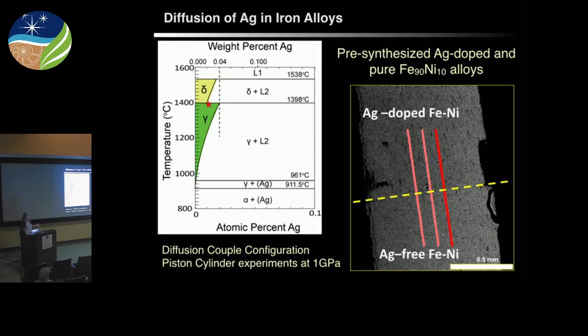Okay, so we did something similar. We did diffusion experiments again. These are a bit more traditional diffusion couple experiments that were measured using the electron microprobe. The one thing that was a bit difficult about these experiments, and I was surprised by this when I first started learning about it, is that silver is super not soluble in iron at all. Here's the iron-rich area of the iron-silver phase diagram, and this is atomic percent silver, and this is the region you have to be in to get silver dissolved in your sample. There's not a lot of silver in iron meteorites either, so it is fine. But that's probably why there was not a lot of information in the literature about silver diffusion in iron.